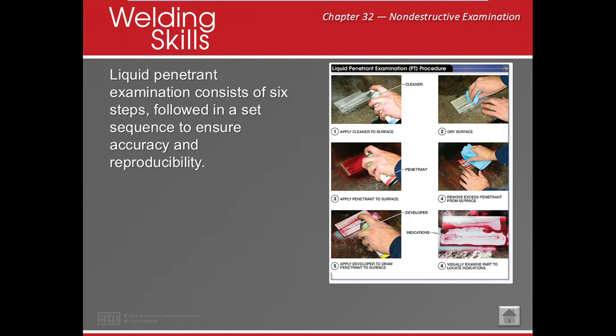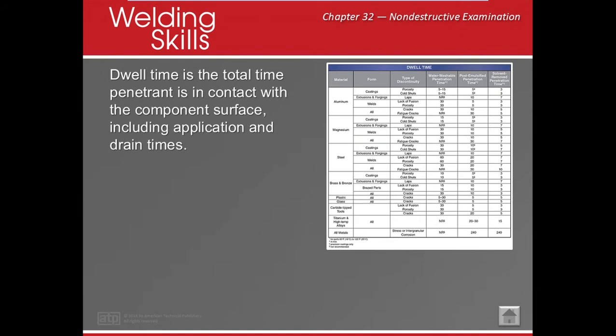After the dwell time, we clean off the penetrant — not excessively, just enough to see any indications — and then apply the developer. The developer, which used to be flour and chalk but is now a powdery substance, sucks up any penetrant trapped in crevices or holes, making them visible. Dwell time is defined as the total time the penetrant is in contact with the component surface, including application and drain times.